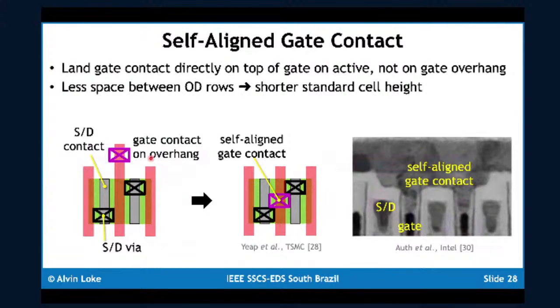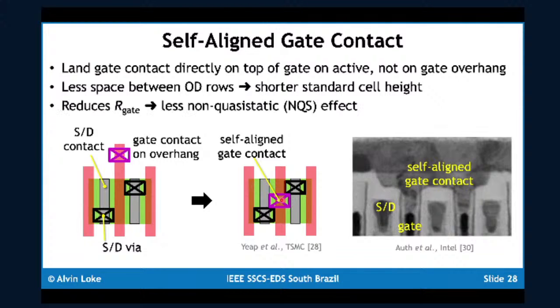So self-aligned gate contacts is a new feature that was introduced by TSMC in 5 nanometer. The idea here is that we no longer need to land the gate contact on the gate overhangs. We can actually land the gate contact directly on top of the gate, on top of the diffusion. And so this allows us to reduce the standard cell height and therefore reduce the overall area of a standard cell. It also benefits by reducing non-quasi-static effects because you have less effective gate resistance.